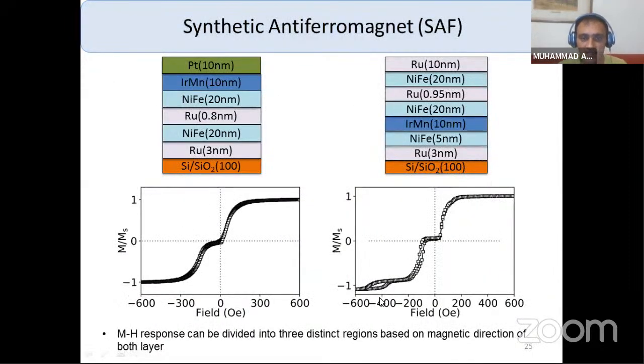So different synthetic antiferromagnets were prepared. You can see here this one with a ruthenium thickness of 0.8, and then this one with a seed layer with a ruthenium thickness of 0.95. Here you can see the respective static magnetization behavior of a SAF.